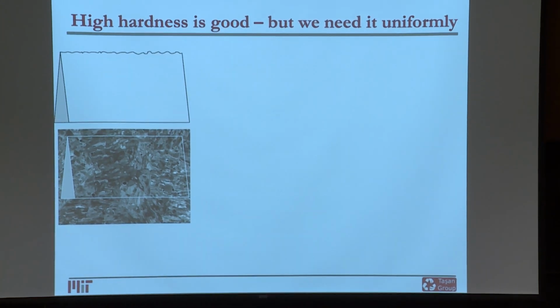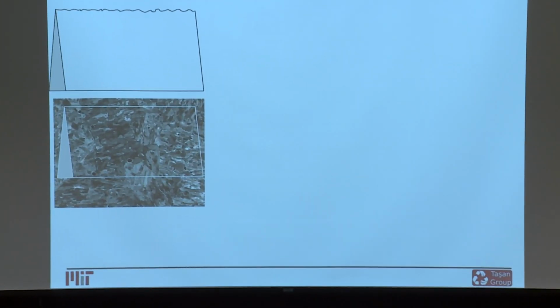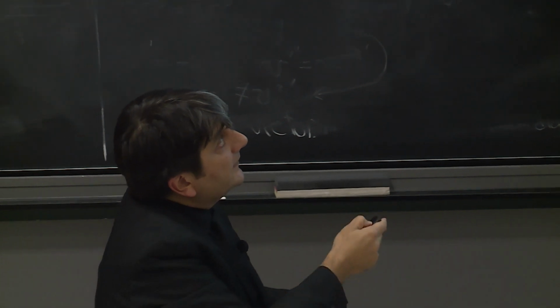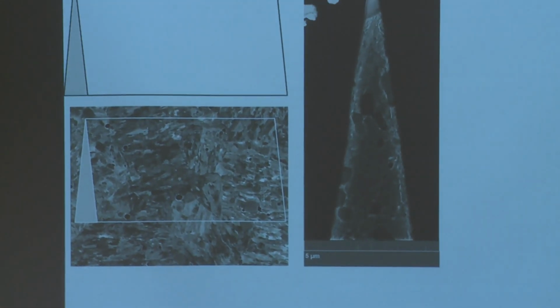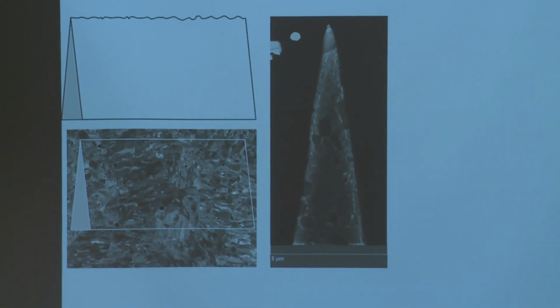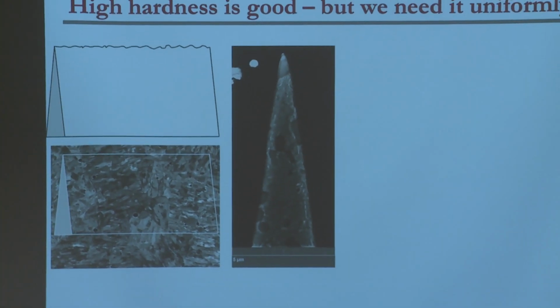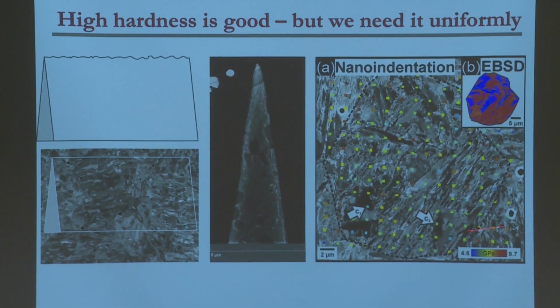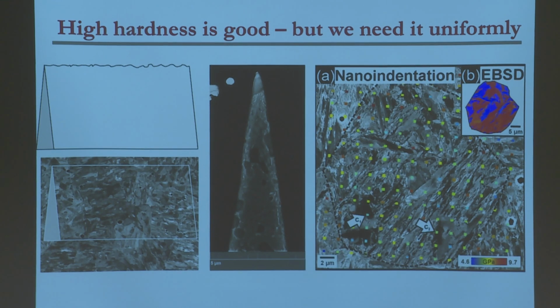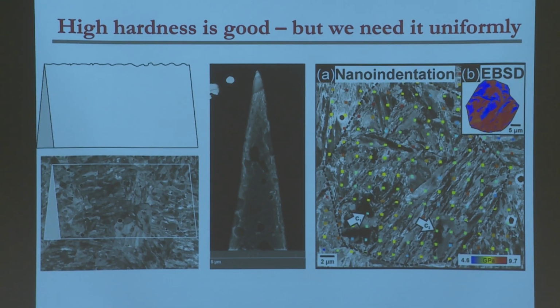As you make a blade out of a material, of course, at the tip of that blade, you are selectively choosing some microstructural features to be there alone. So here is one example, for instance, one cross-section that Gianluca produced, which had a carbide at the tip of this blade, which has a very different local behavior than other martensitic regions, lath martensitic regions. And even without the carbides, actually, it's been shown that martensite can have a lot of heterogeneity in its structure.